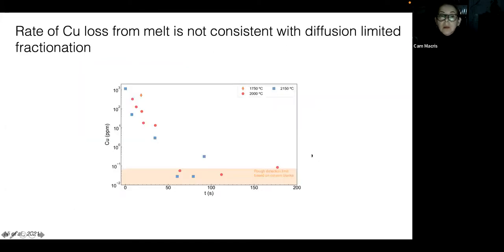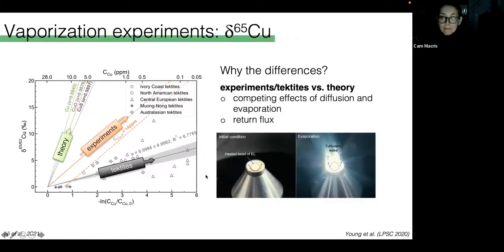Also, the rate of copper loss from the melt is not consistent with diffusion-limited fractionation. So this is the same figure you've seen before, where it doesn't take long before you start to lose so much copper you can't even detect it. So another culprit for the offset between the experimental and theoretical alphas could be the role of return flux in